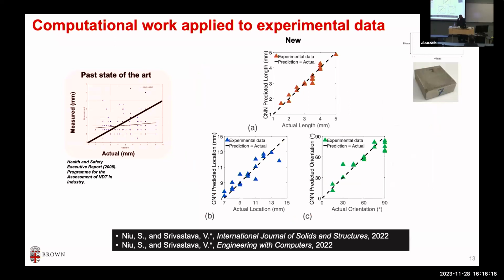But here's the finding. This was a study by government and industry, the latest state of the art in the lab, where you try to measure the length of a crack that you cannot see. This 45-degree line is actual versus measured. If you have 100% accurate measurement, the dots will lie on the 45-degree line. Anything away from it is the amount of error you see. And this is our prediction.